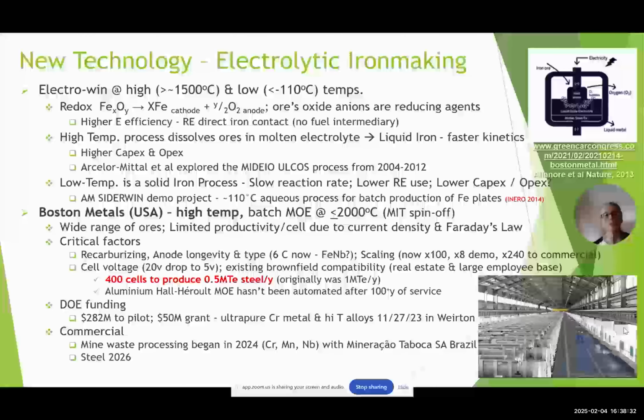Low temperature is solid iron processing, slower rate, lower capex, lower renewable energy, and ArcelorMittal Siderwin is a demo project at 110 degrees. Boston Metal is the most well-known, I believe, running at less than 2,000 degrees. It's an MIT spin-off. It can process a wide range of ore, but it's limited in productivity by the cell and current densities in Faraday's law. Critical factors are recarburizing, anode longevity and type, and the scaling.